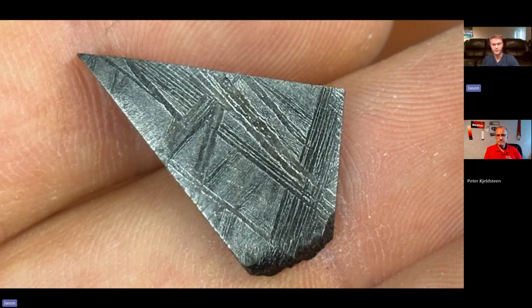Say we have an asteroid, right? And we say we have 10% nickel in that asteroid, and we have 90% iron in that asteroid. And say this asteroid went through a celestial impact and it's very hot. And so when it's very hot, everything is going to be taenite. That whole asteroid is going to be taenite. And so taenite, I said, is a low iron phase, but we have 90% iron in that asteroid. So even though we have a considerable amount of iron in the asteroid, because it's so hot, the crystal lattice of the taenite has enough energy to accommodate that iron. But as we begin to cool, that crystal lattice loses energy. And so it has less and less energy to accommodate that iron. And that iron wants to get out.